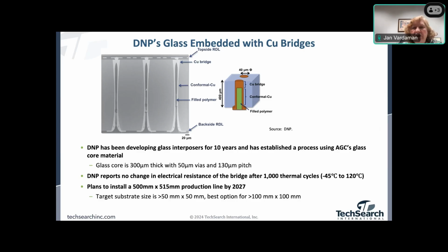DNP's been working on this for quite some time. They have a number of different test vehicles. They've 10 years of work in this. They use AGC's glass core material. The glass core is about 300 microns thick with 50 micron vias and 130 micron pitch. They've done a lot of publications of their no change in electrical resistance on their bridge version after 1,000 thermal cycles. And they plan to install a production line by 2027.